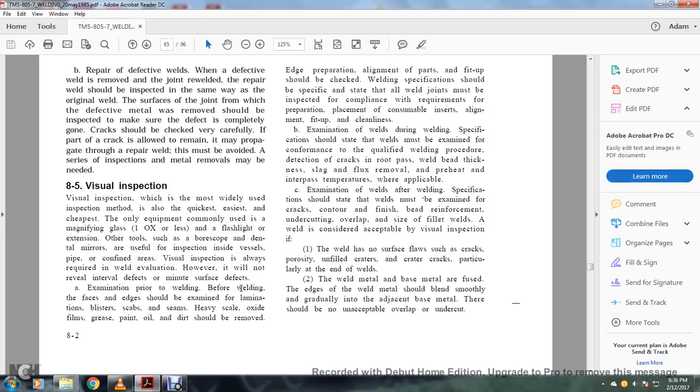Examine prior to the welding. Before welding, the faces and edges should be examined. Laminations, blisters, scabs, or seams, heavy scale or oxide films, grease, paint, oil, or dirt should be removed. Edge preparation, alignment of the parts, and fit-up should be checked with the welding specifications. It should be specified that all the welding joints must be inspected for compliance with the requirements for the preparation, placement, consumable inserts, alignment, fit-up, and cleanliness.